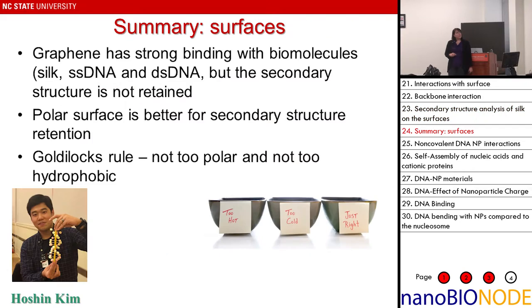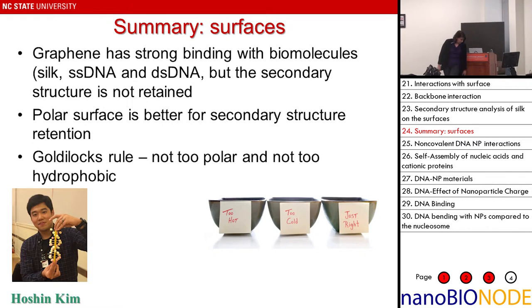Looking at average change in secondary structure: for graphene, the protein denaturates (more coil structures form). Silicon dioxide also shows more coil structure formation. However for graphene oxide, disordered coil structures are decreasing and secondary structure elements are increasing. So overall, graphene has very strong binding with biomolecules but secondary structures are not retained. Polar surfaces are generally better for secondary structure retention, but there is a 'Goldilocks' rule — not too polar, not too hydrophobic — and more investigation is needed.